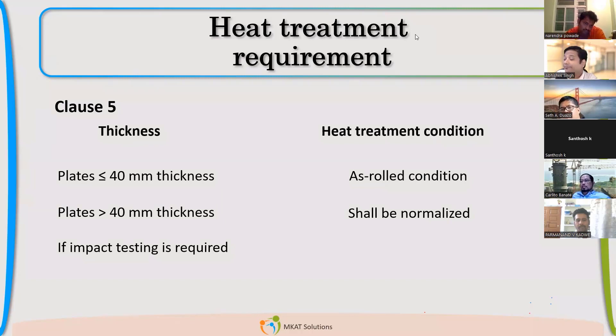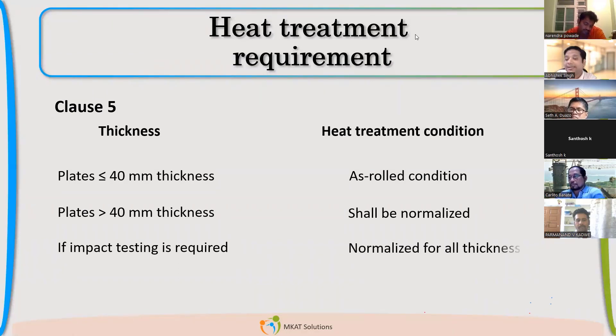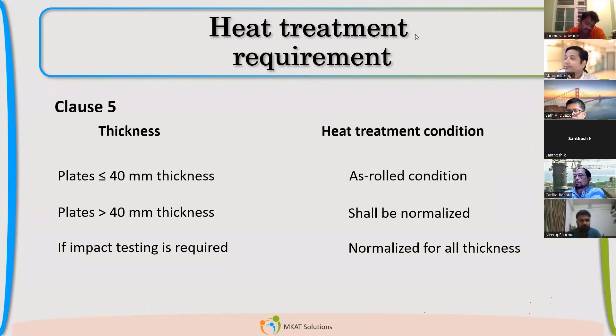Now, if we have an impact testing requirement for our job — if you have to perform impact testing, you have done the calculation and MDMT is not qualifying — so you have to do impact testing. If it is already concluded that impact testing is required, then normalizing is required for all thicknesses. Whatever you order, even a 10mm plate, you will have to go for normalized.